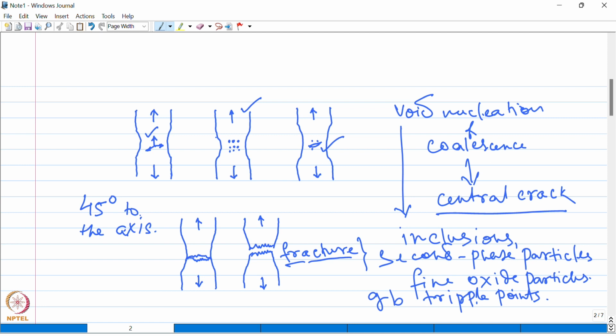And if you see the finer details, the fracture process first occurs locally at narrow bands of high shear strain. And these shear bands are located roughly at some angle close to 50 to 60 degrees to the transverse direction. So along these bands, sheets of voids are first nucleated as the material is strained. And these voids will grow and coalesce as we have discussed before, leading to local fracture of the void sheet. Thus the crack growth in ductile fracture essentially occurs by a process of void coalescence.